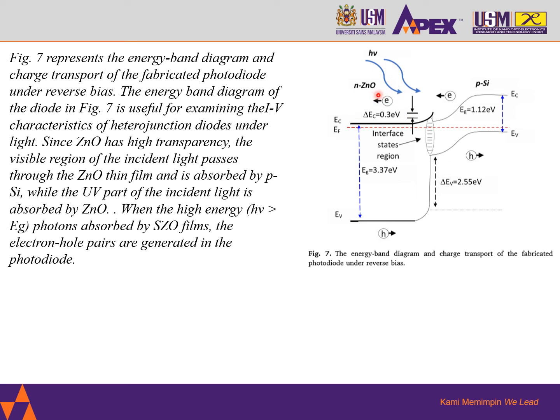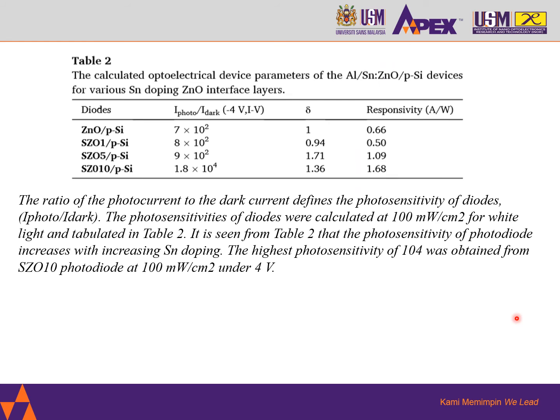Here you can see the photodiode energy band where the electron-hole pair is generated. The ratio of photocurrent to dark current defines the photosensitivity of diodes: I_photo over I_dark. The photosensitivities of the diodes were calculated at 100 milliwatt per square centimeter for white light and tabulated in Table 2. It is seen from Table 2 that the photosensitivity of the photodiode increases with increasing tin doping. The highest photosensitivity of 10^4 was obtained from the SZO10 photodiode at 100 milliwatt per square centimeter under 4 volt.